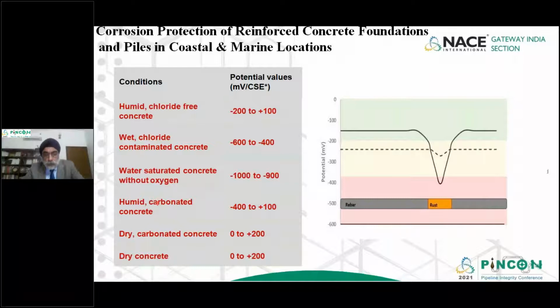And then if the values are between minus 400 to plus 100 millivolt, the concrete is carbonated. And similarly, we can find out if it is a dry concrete or a dry carbonated concrete. If it's a dry concrete, we will have a potential of 0 to plus 200 millivolt, and this indicates no corrosion. So by logging these values of the potential of steel in concrete with respect to a copper sulfate electrode, we can find out the status of what is happening in the rebar, the same way we do measurements of pipe in soil. This is a very important test to be conducted by engineers to ensure that the steel in foundations or steel in pile caps is not corroding.